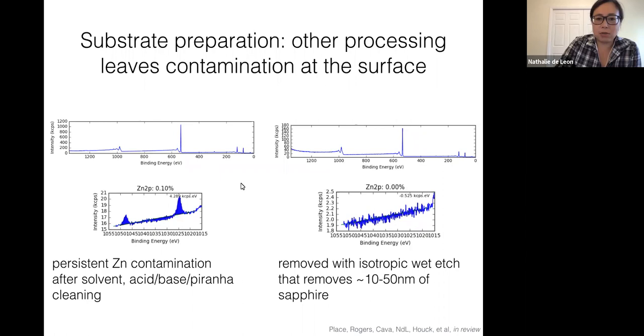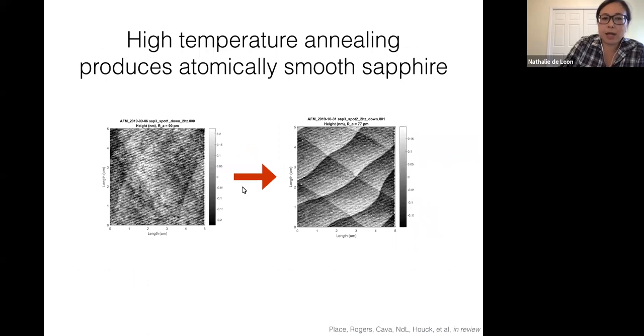Additionally, we can do X-ray spectroscopy to see if there are any heteroatom contaminants, and what we found is that there was processing that left a bunch of zinc contamination at the surface. This was very, very difficult to remove. What we developed was an isotropic wet etch that removes the top few nanometers of material, and that seems to get rid of this heteroatom contamination. Finally, we can do high temperature annealing in air, and that recovers a surface where you can actually see these step edges in AFM. So we have close to atomically smooth sapphire surfaces.